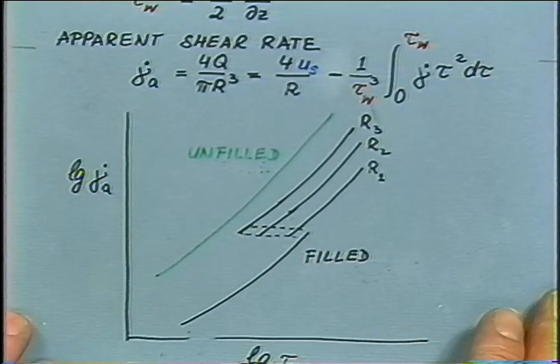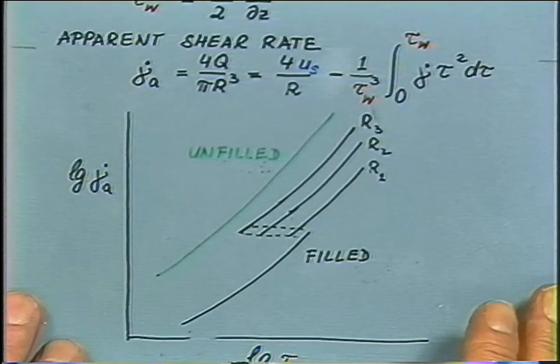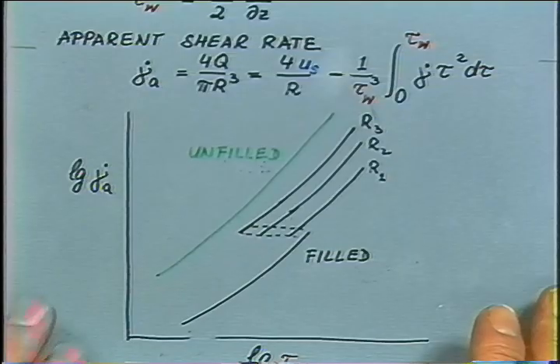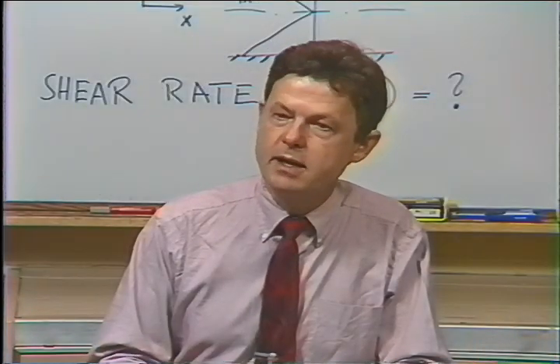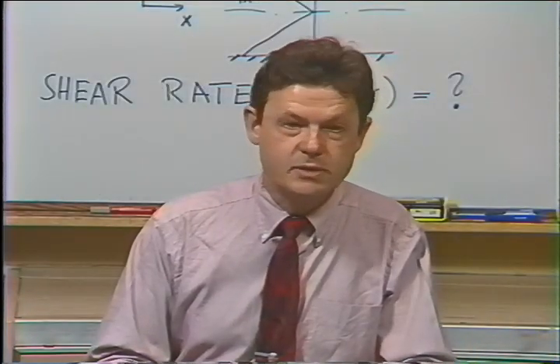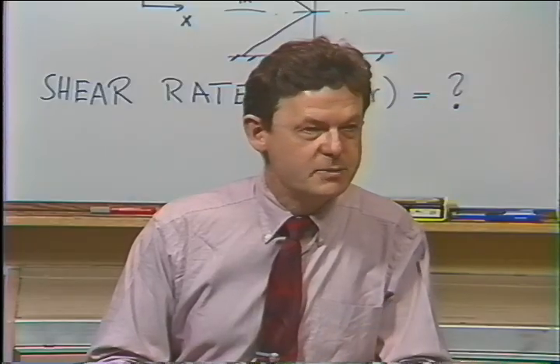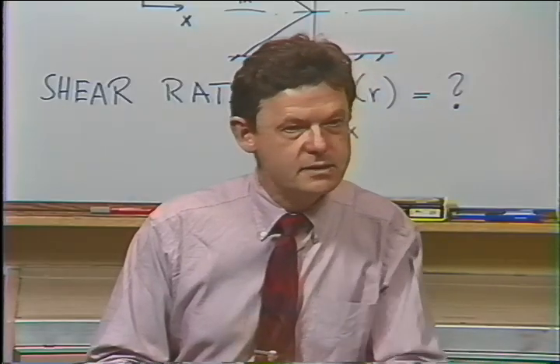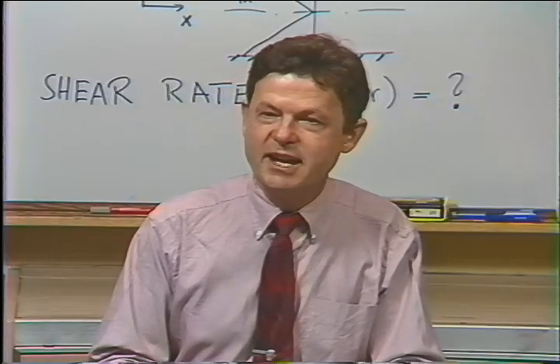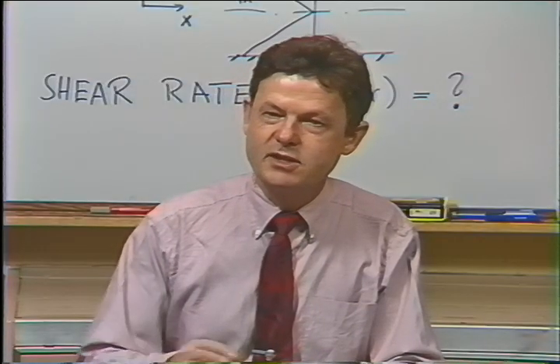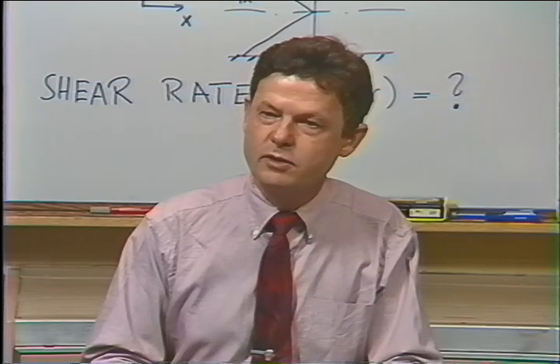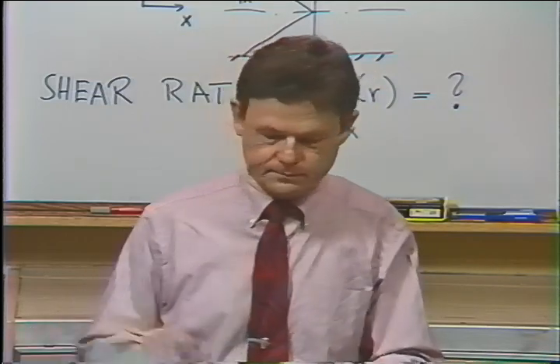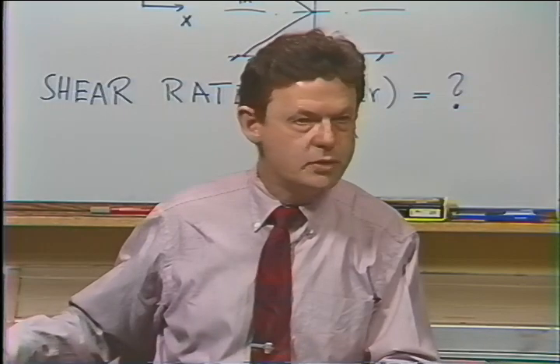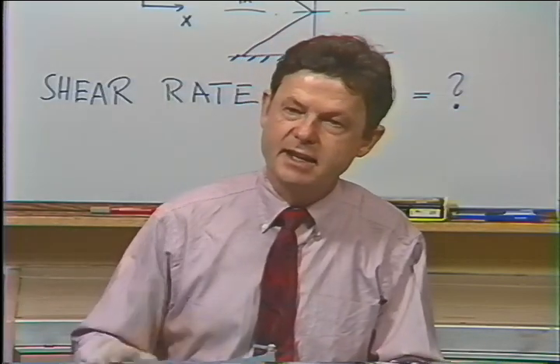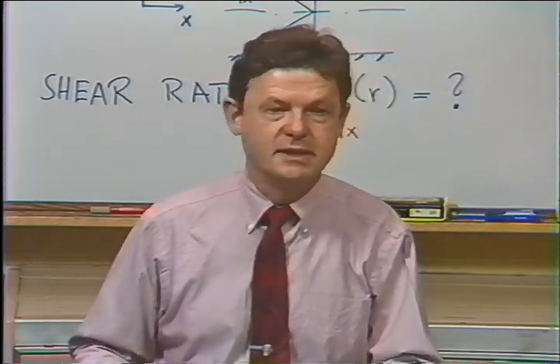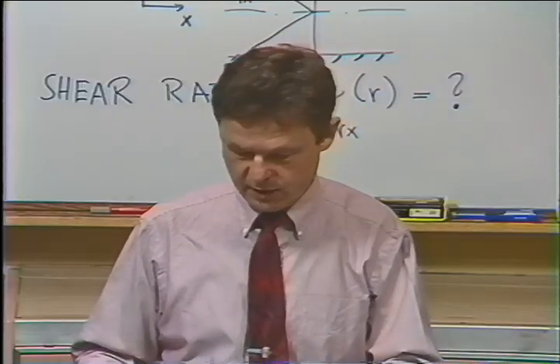So here you have a simple procedure to find out whether your material slips or doesn't slip under the shear stress conditions which you are imposing in whatever experiment you're doing. It's a neat way of finding out the transition, the stick-slip transition of your specific material. It goes back to Mooney, who analyzed this data and then calculated the slip velocity as a function of the shear stress at the wall.